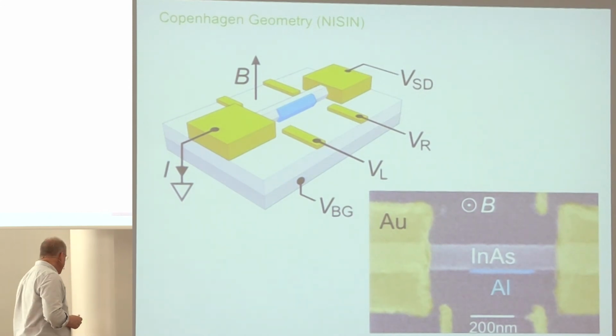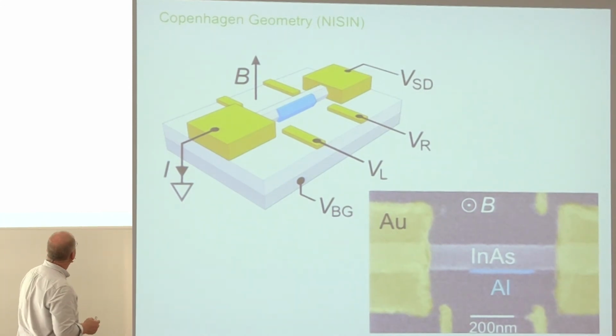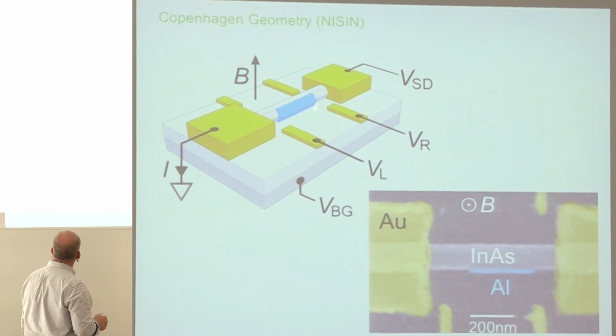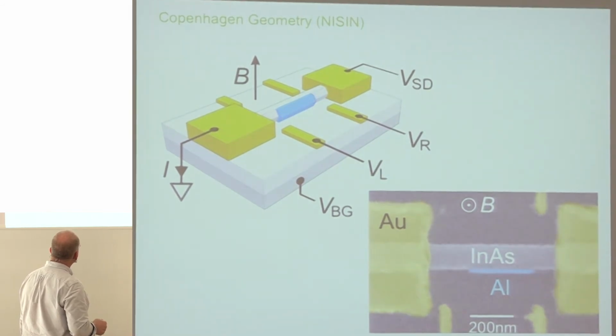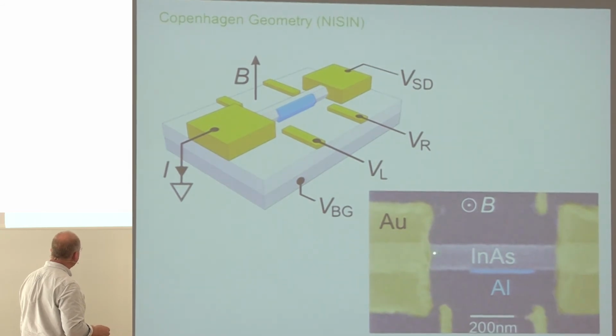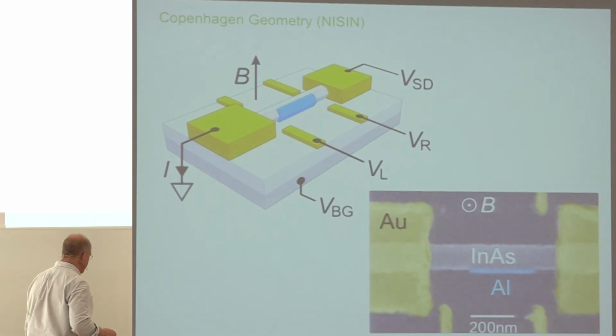There's another geometry that I want to talk about in the remaining few minutes, which looks more like a quantum dot. It's one where most of the superconductor has been removed, except for a small patch. You can see here in an electron micrograph, here's the indium arsenide nanowire. It's pretty big, about 100 nanometers in diameter. And a very small amount of this epitaxially grown aluminum is left behind, and almost everywhere else it's been removed, and gates are around it to make an isolated superconducting island.